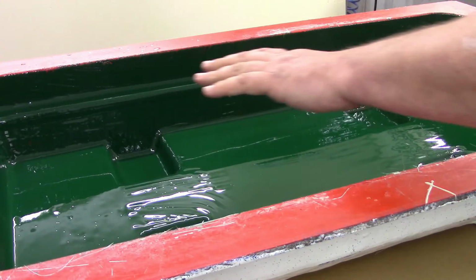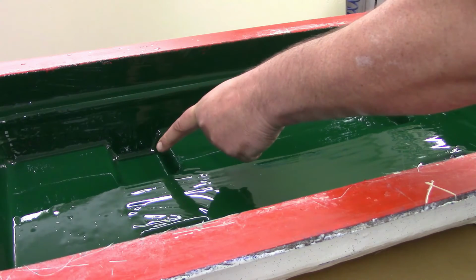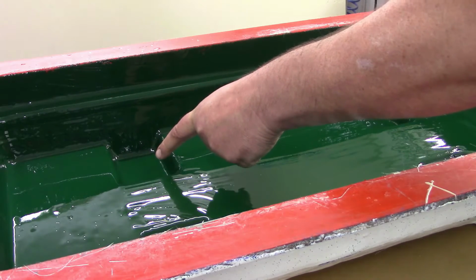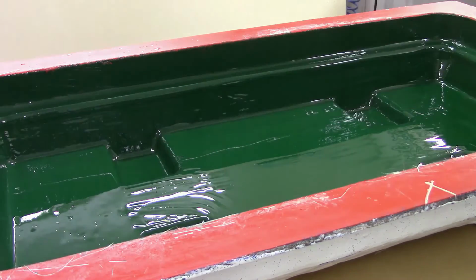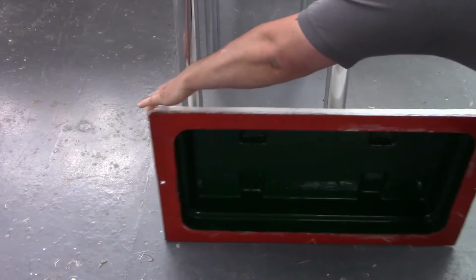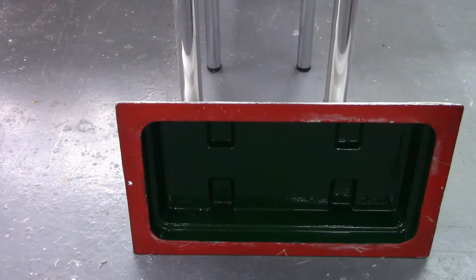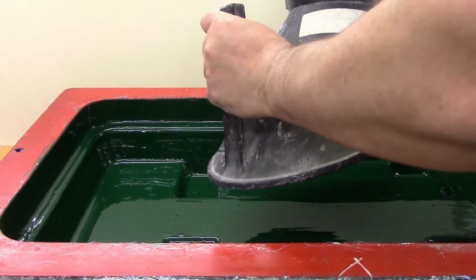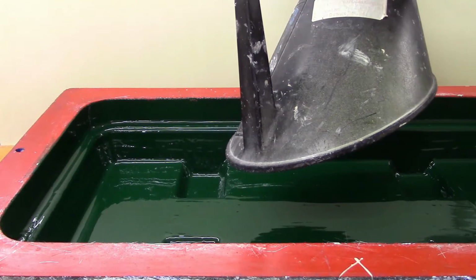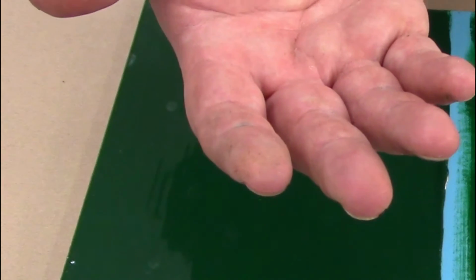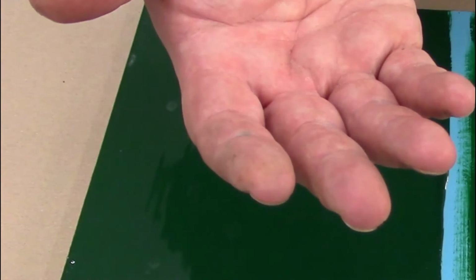This is because the styrene vapours collect at the deepest areas of the mould and can slow the Gelcoat's curing process. To combat this, simply turn the mould on its side to help the vapours flow out, or use a localised extraction system, or simply fan the vapours out of the mould. The Gelcoat is ready once no colour is present on your fingertips.